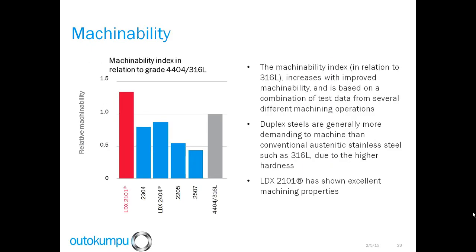We look at the machinability. The machinability index in this plot increases with improved machinability. The chart shows that the machinability of most duplex grades is more demanding than 316L. However, LDX 2101 has shown excellent machinability compared to 316L when the appropriate machining parameters such as cutting speed and cutting depth are optimized for this grade.